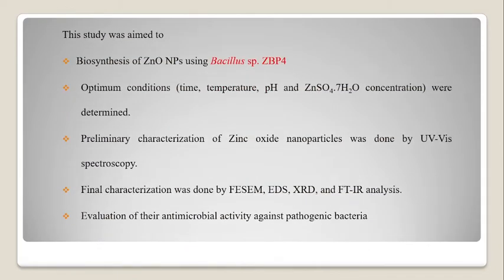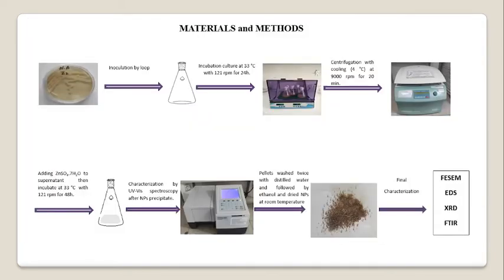This study aimed to biosynthesize zinc oxide nanoparticles using Bacillus species ZBP4 and detect the optimum conditions like time, temperature, etc. Preliminary characterization of zinc oxide nanoparticles was done by UV spectroscopy, and final characterization was done by FESEM, XRD, and FTIR. Finally, evaluation of their antimicrobial activity against pathogenic bacteria.